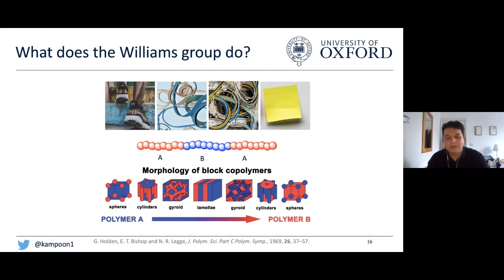And these are typically formed of what we call tri-block copolymers, meaning that there's almost like a polymer sandwich with two different types of polymer either side of another type. So we call these ABA block copolymers. What we do here is we choose a polymer for the A block that is very hard and very rigid, and one for the B block that's very soft and flexible. By chaining these together we get both properties. We get a material that's flexible, extendable and stretchy, but also has really good mechanical strength because of those harder